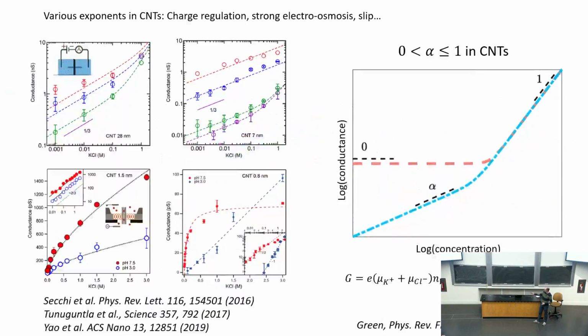And so a recent work here by Yoav Green out of Israel suggests that the slip length we just talked about actually kicks in here, and it can amplify your exponent alpha to go anywhere between 0 and 1. So slip length and also charge at the pore mouth are factors that seem to dominate this regime in carbon nanotubes, but it's not yet fully understood.